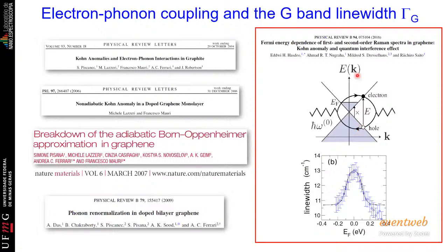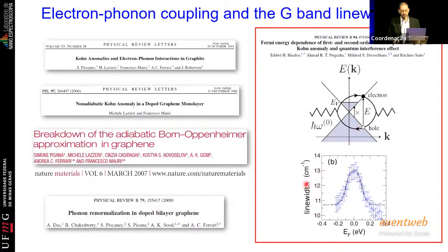And this has been proved very nicely by an experiment where you measure exactly the line width of the carbon-carbon stretching by gate doping the material. So when the material is not doped, it's at 0, means this level here of electrons is at this point. Okay, so when it's at this point, this is full of electrons and this is empty, so you can generate the electron hole pair. But if you move the doping either to negative or to positive side, what you do is you take the level of electrons and you move above the phonon energy. And when you fill with electrons up to here, because of the Pauli exclusion principle, the phonon cannot decay into an electron hole pair anymore because it's full up to here. And this also happens if you empty down here, because there will be no electrons to do this